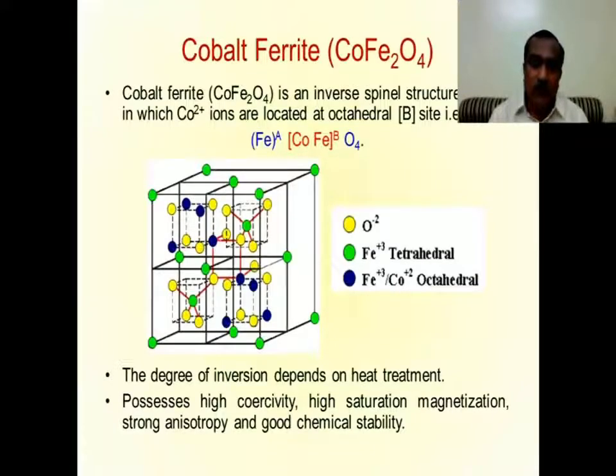On the basis of the occupancy of the elements in a ferrite, the general formula for ferrite is MFe2O4. M represents the divalent metal ions like cobalt, nickel, zinc, etc. And based on the occupancy of the cations, cobalt, zinc at the tetrahedral site or octahedral site, these are classified as normal, inverse, and random spinel.